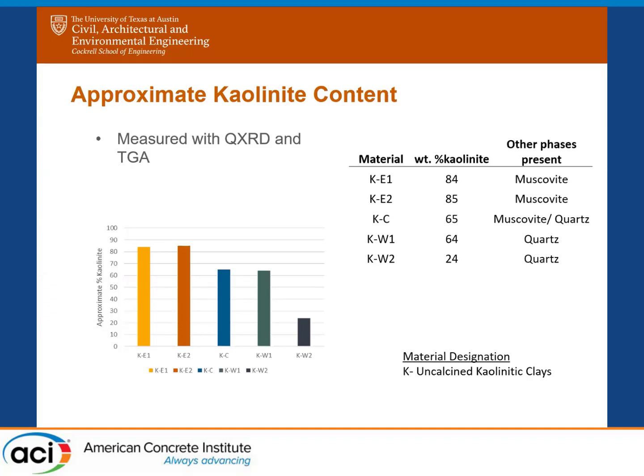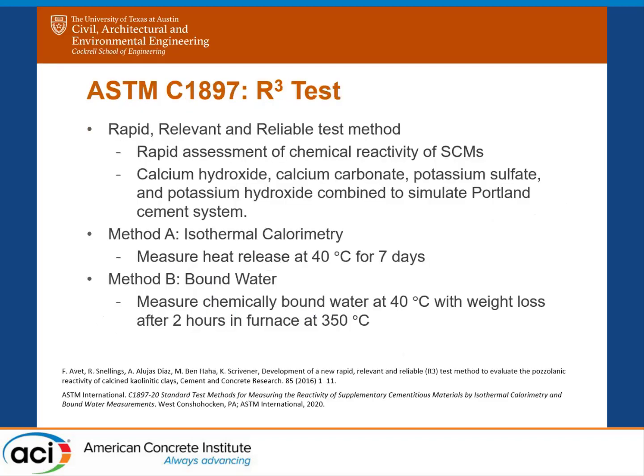So it was shown that the 85% may not be considered a moderate purity clay anymore because it's pretty high purity, and at least in the reactivity data was closer to metakaolin. But this around 65% is definitely moderate purity kaolinite, and then 24% is on the lower end. So the other phases present for the higher purity ones is muscovite, and the lower purity is mixed with quartz.